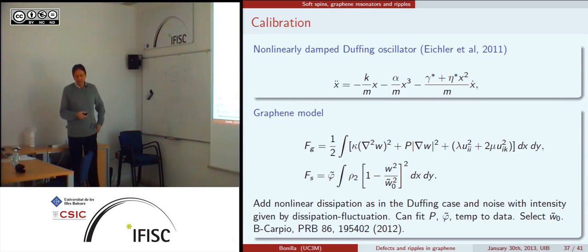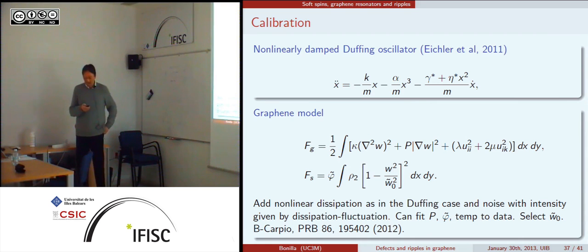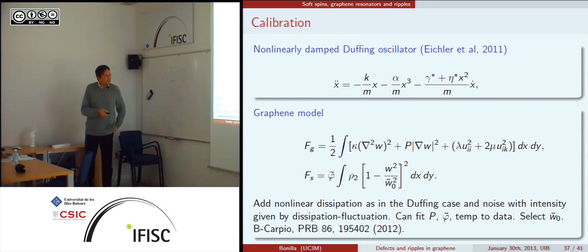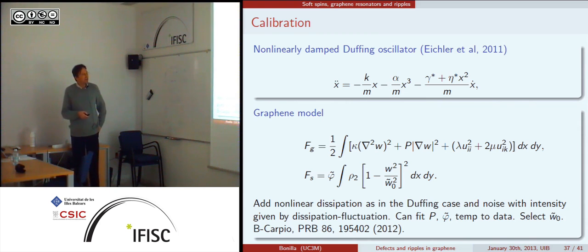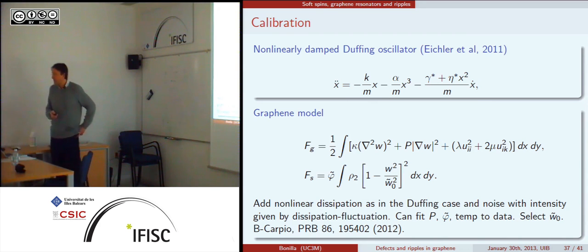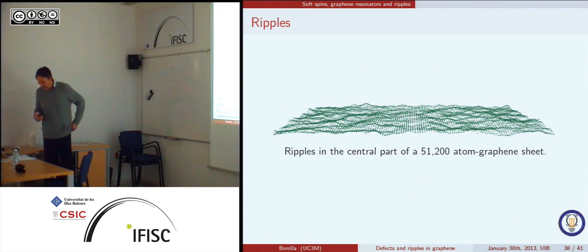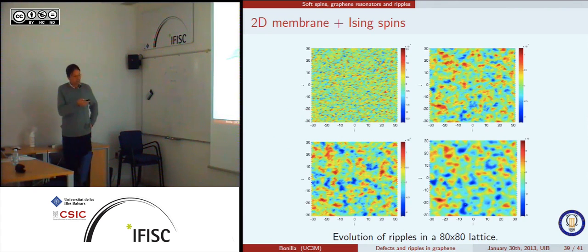Now, if you look at the evolution of the fundamental mode of that, it turns out it's essentially a Duffing oscillator if you add damping appropriately. Of course, if you have damping, you should also have a noise, according to the fluctuation dissipation theorem, which should also be taken into account. So with this kind of model, we were able to fit all the parameters with the measured data in the Duffing equation, except that we had one free parameter, which is the depth of the well, for instance. Okay. So modulo that parameter, you get ripples, and this is the central part, a situation similar to the one I showed before.